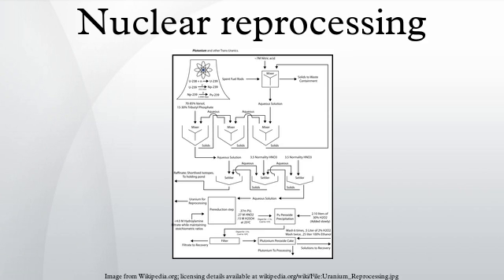The mixed actinides produced by pyrometallurgical processing can be used again as nuclear fuel, as they are virtually all either fissile or fertile, though many of these materials would require a fast breeder reactor in order to be burned efficiently. In a thermal neutron spectrum, the concentrations of several heavy actinides can become quite high, creating fuel that is substantially different from the usual uranium or mixed uranium-plutonium oxides that most current reactors were designed to use.